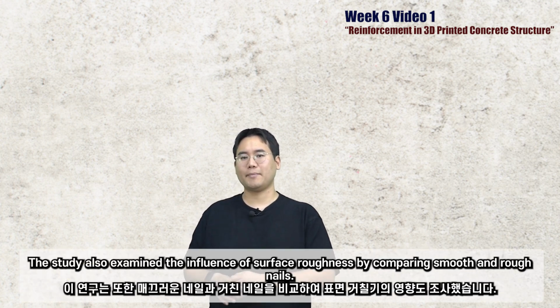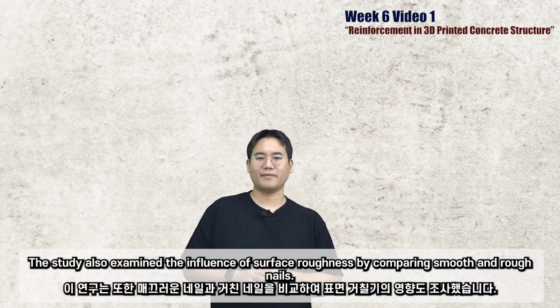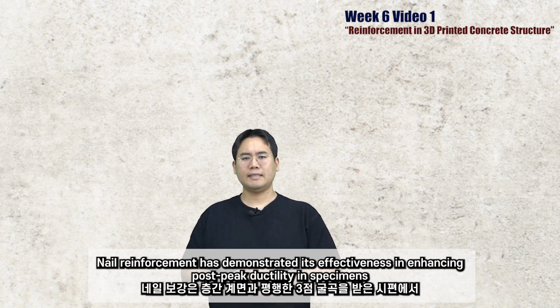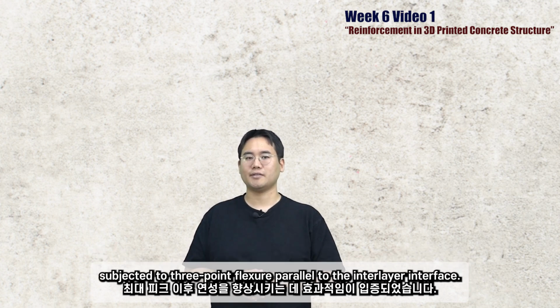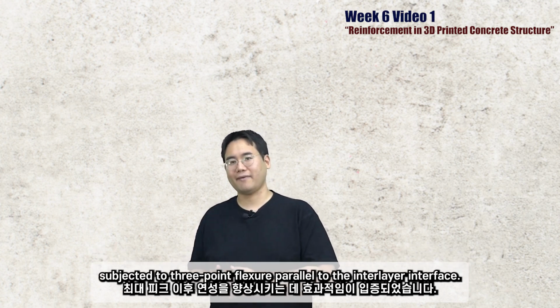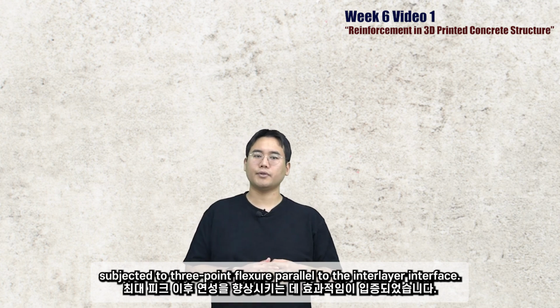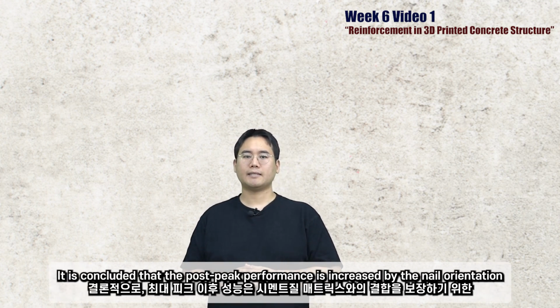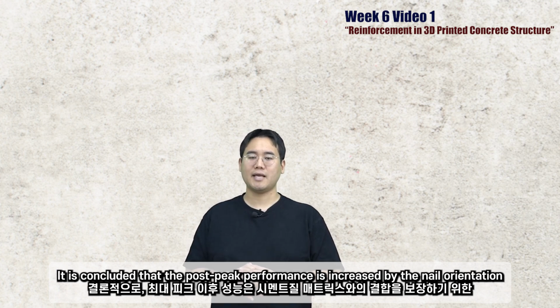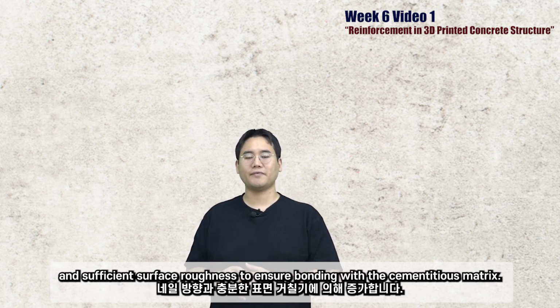The study also examined the influence of surface roughness by comparing smooth and rough nails. Nail reinforcement has demonstrated its effectiveness in enhancing post-peak ductility in specimens subjected to 3-point bending tests parallel to the interlayer interfaces. It is concluded that post-peak performance is increased by the nail orientation and also the sufficient surface roughness of the nail to ensure bonding with the cementitious matrix.